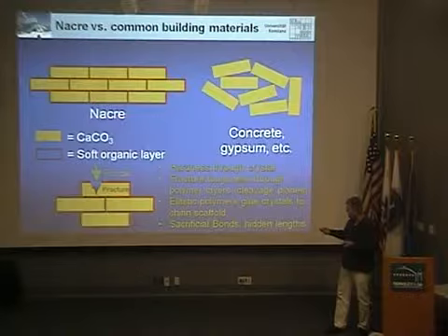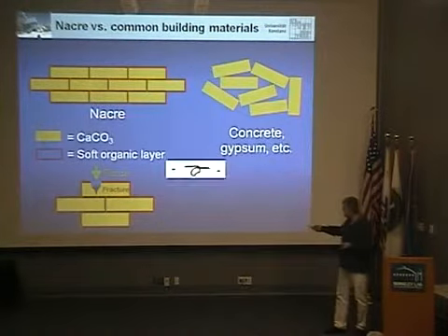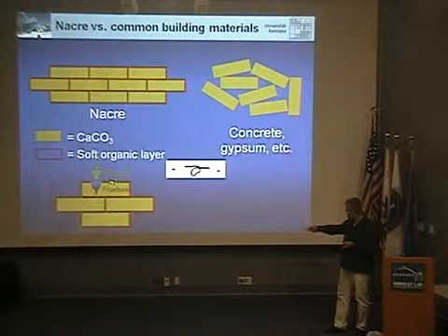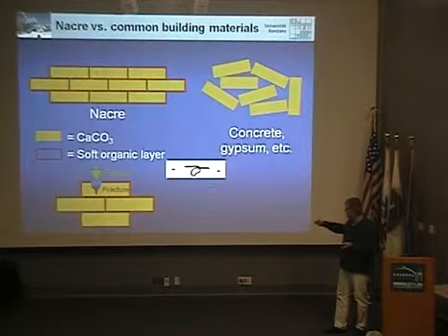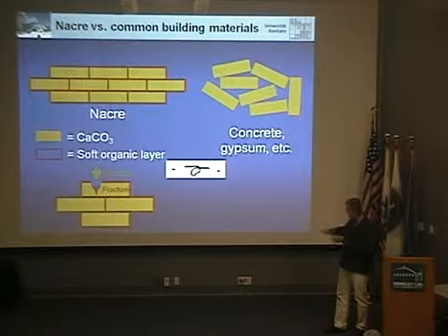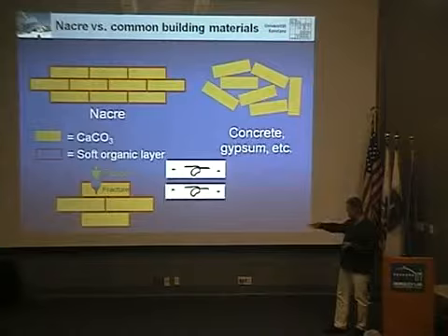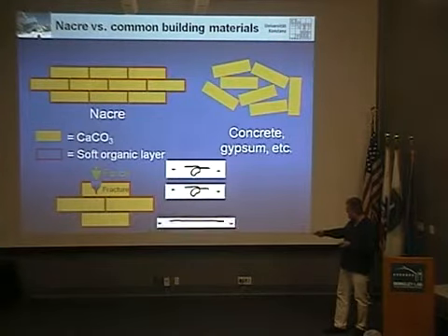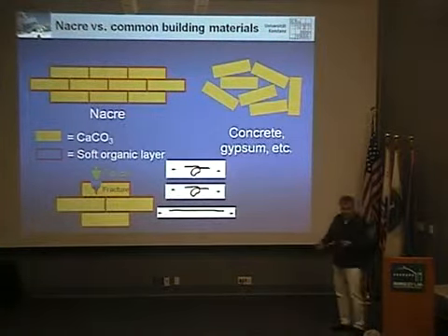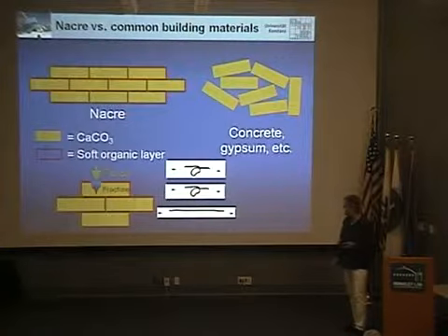And nacre is even more complex. The inorganic crystals are glued to the organic layers by proteins, which have sacrificial bonds, which also dissipate energy further. So if you pull at them, the bonds may loosen and they may stretch. So that's another mechanism to dissipate the energy.